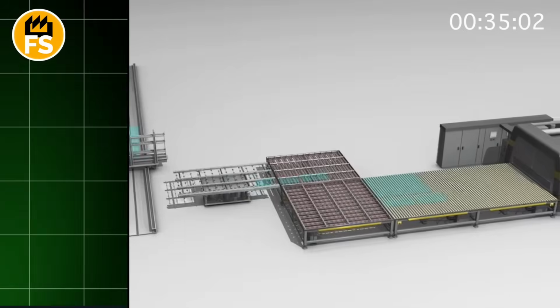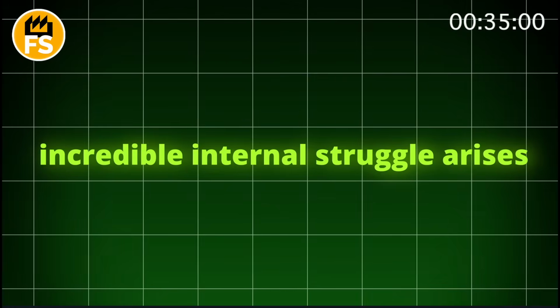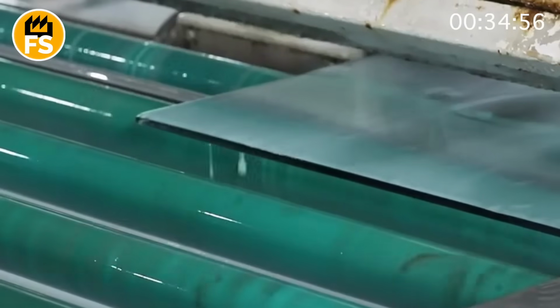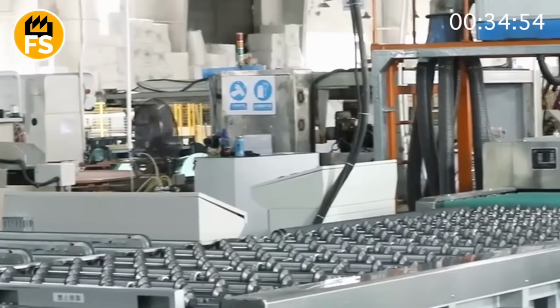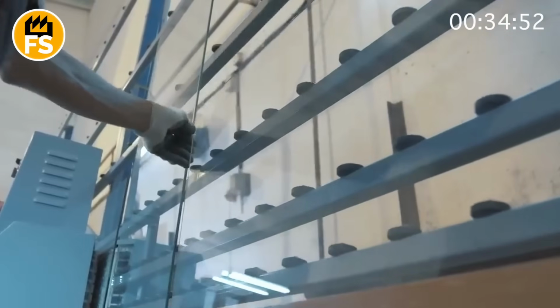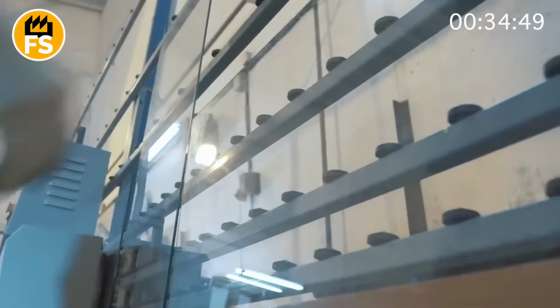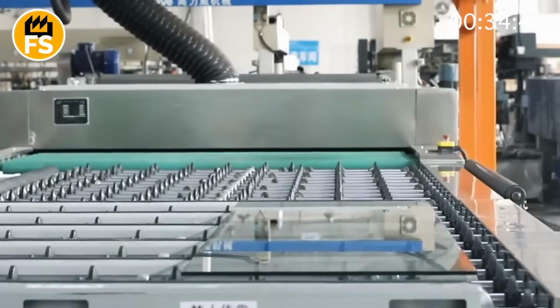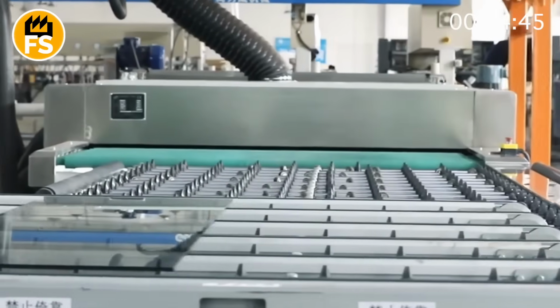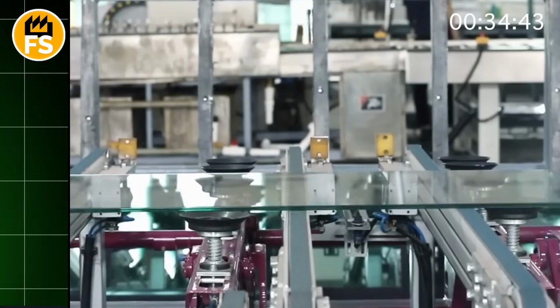As a result, an incredible internal struggle arises. The cooling hot core pulls the outer layers inward, creating a state of huge tension in the center of the glass, like a stretched string. In response, the outer layers are under an incredible force of compression. In essence, the glass turns into a stress sandwich. Two strongly compressed outer layers and a tense, stretched inner layer.